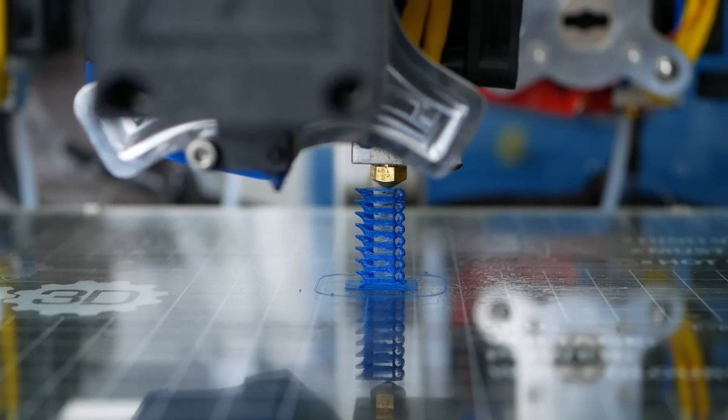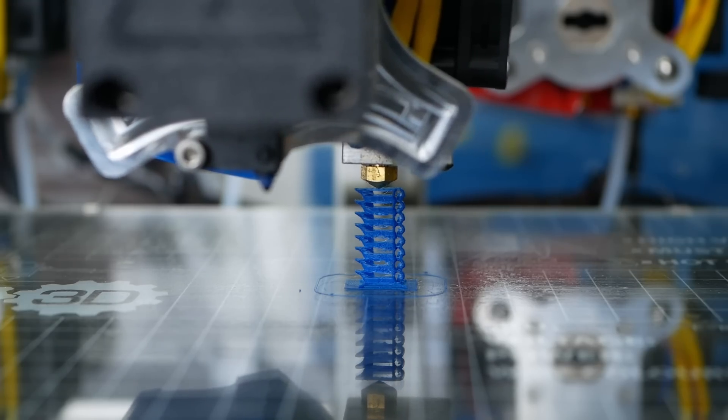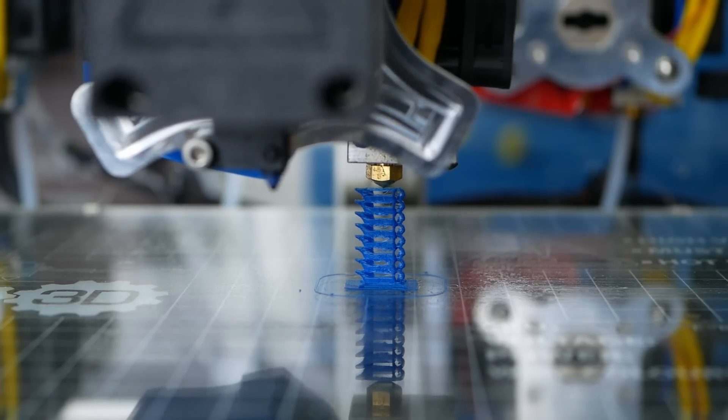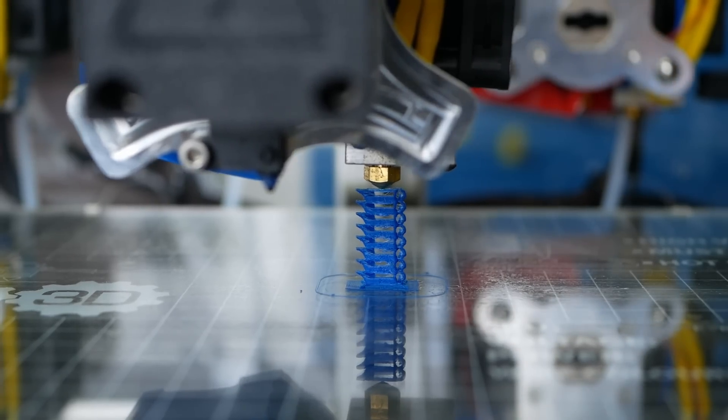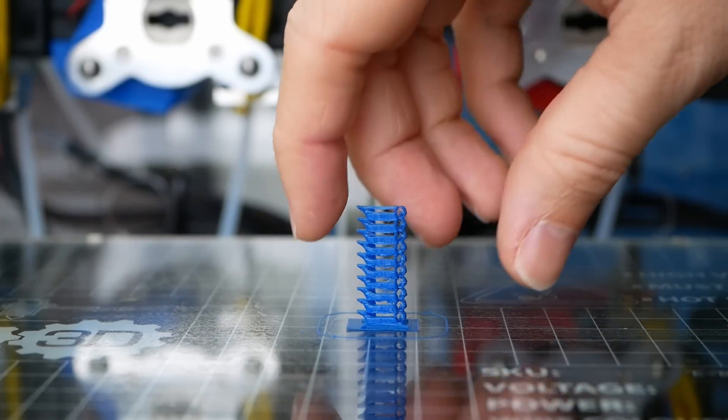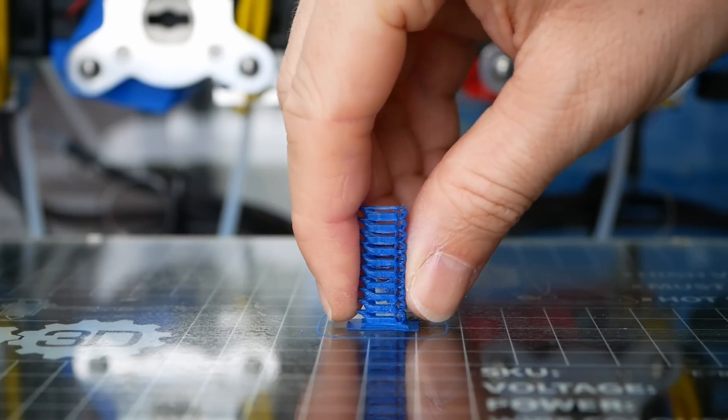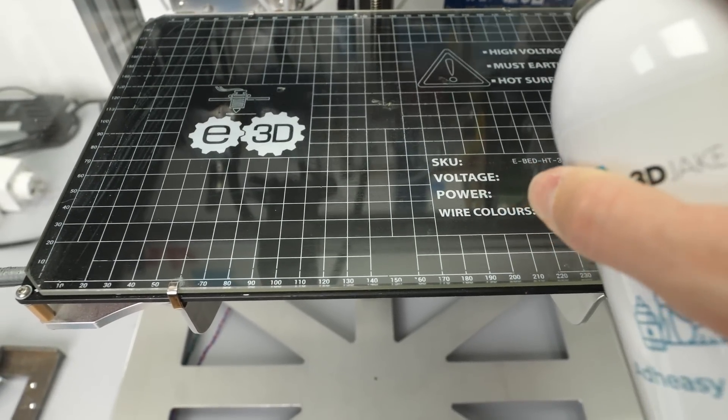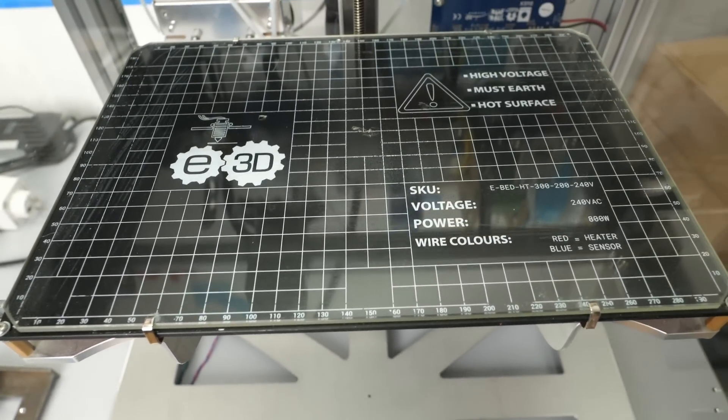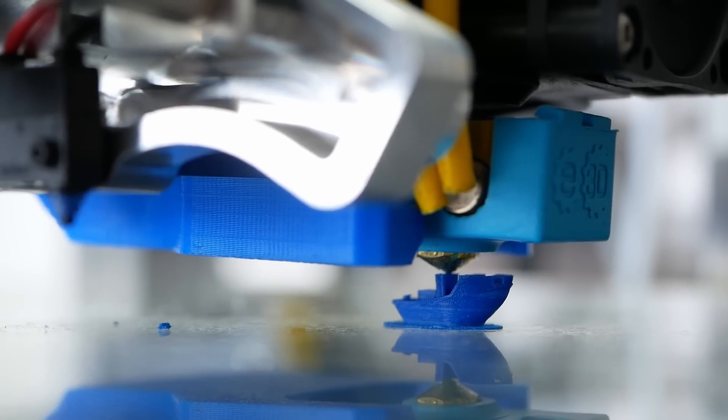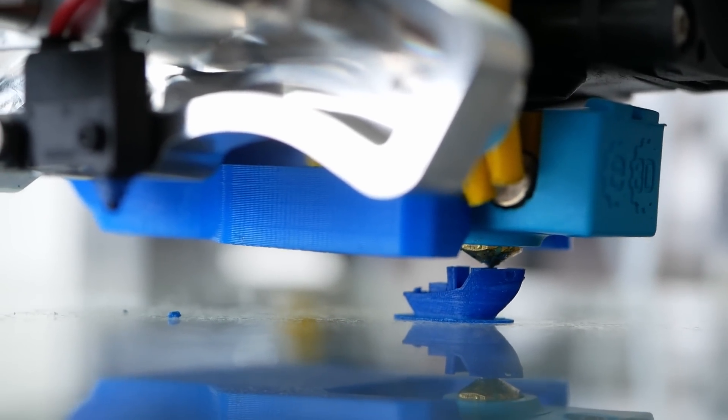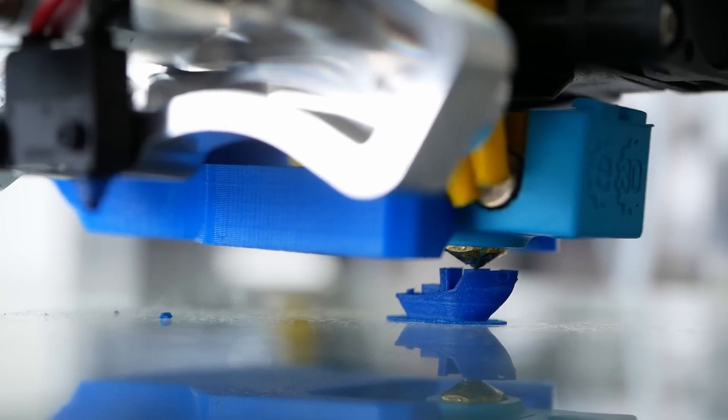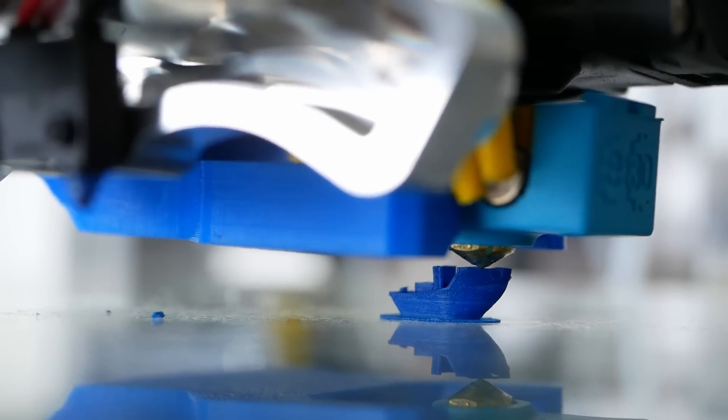Because we print so slowly, the material stays in the melt zone for way longer than usual, so we can lower extrusion temperatures significantly because the material will always be equally heated through. I went with 180 degrees Celsius for my PLA. I printed on a raft and used a bed adhesion spray so that I can lower the bed temperatures to only 30 degrees Celsius after the first layer. If the bed is too warm, it radiates heat to the part, preventing it from properly solidifying and therefore decreasing print quality.